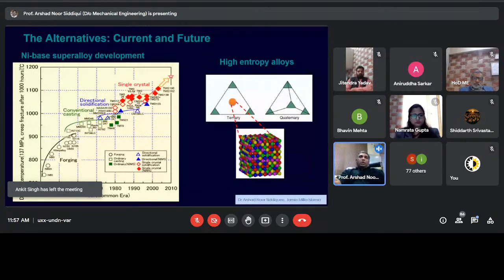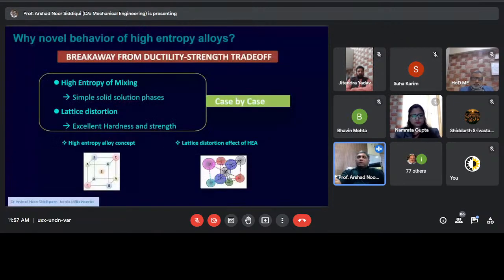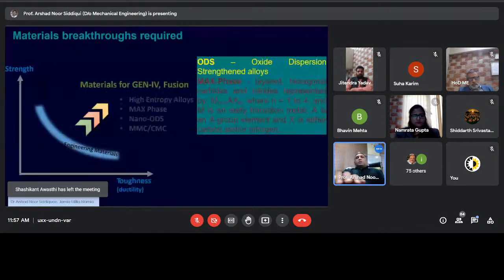So the high entropy alloys work on a different concept than the typical and conventional alloys, which are governed by the Hume-Rothery rules. They are not governed by the Hume-Rothery rules. Rather, they are governed by the configurational entropy of mixing. This is how it is. A quick scan through the materials.